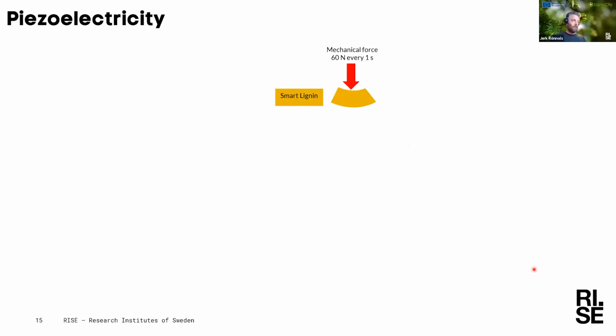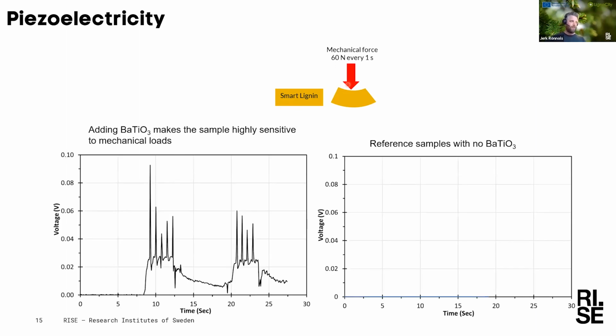The other thing we investigated was the piezoelectricity. So we took the same lignin elastomer and blended in barium titanate instead, which is a good agent for introducing piezoelectric properties to a material. So in this investigation, where you will see the graphs soon, we have our lignin, it's the yellow thing here, and an instrument is applying a mechanical force of 60 newtons once every second. And then we will see, does that generate a current? And what the graph here on the left shows is that, yes, every time the force is applied, we see a spike in the voltage.